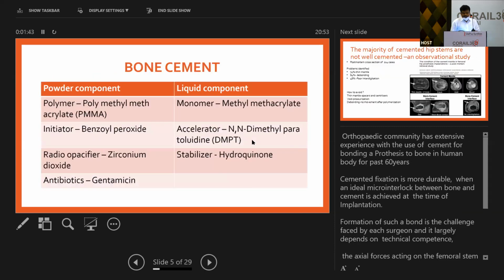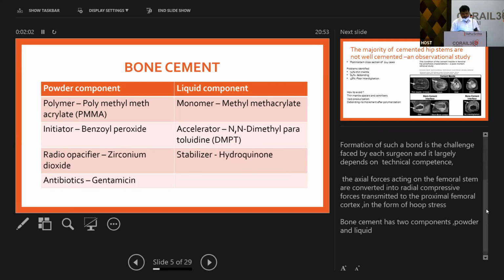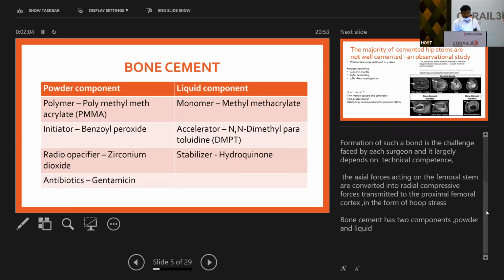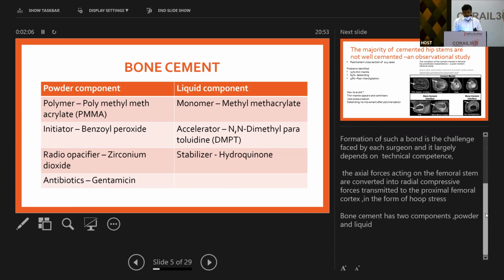The orthopedic community has been extensively experienced with the use of cement for the past 50 years. Cement fixation is more durable when ideal micro interlock between bone and cement occurs at the time of implantation. Formation of such a bond is a challenge each surgeon faces and largely depends on technique. The cement has two components: a powder component and a liquid component. The powder component has an initiator, the liquid component has a stabilizer. Heat stable antibiotics are mixed with the bone cement.